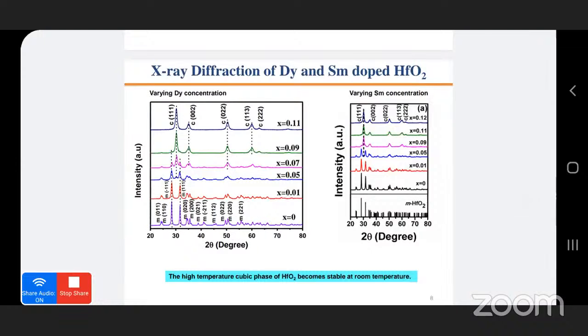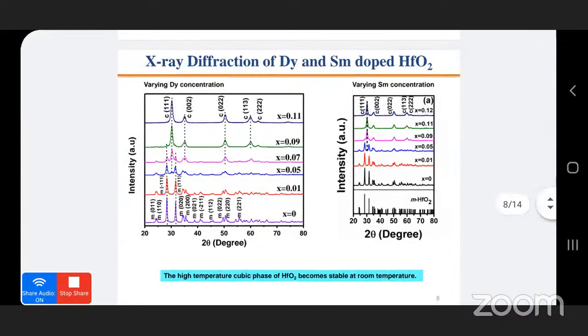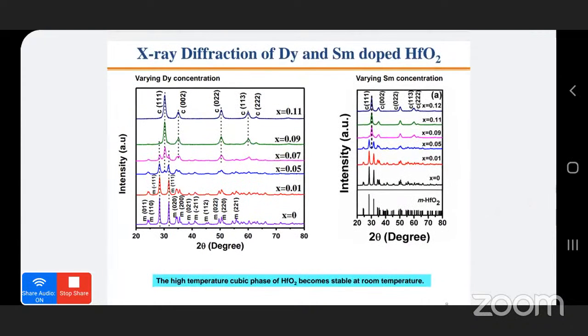The left XRD figure, the X-ray diffraction figure, shows the patterns for Dy-doped hafnia with different Dy concentrations. We can see that for pure hafnia, all the diffraction peaks correspond to the monoclinic phase only. As we increase the concentration of Dy from 0 to 1 atomic percent, there is not much change in the crystallinity, and the crystal system of the hafnia remains monoclinic. But as we increase the Dy concentration further, for Dy 5 atomic percent, along with the monoclinic -111 and 111 peaks, there is one more peak coming between them.